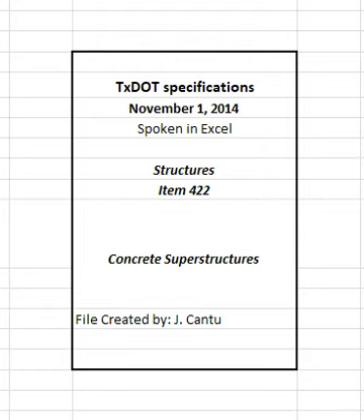of the mat. Provide polyethylene sheeting that is at least 4 mils thick and free from visible defects. Provide opaque white sheeting when the ambient temperature during curing exceeds 90 degrees Fahrenheit. Provide burlap polyethylene mats made from burlap impregnated on one side with a film of opaque white pigmented polyethylene, free from visible defects. Provide laminated mats that have at least one layer of an impervious material such as polyethylene, vinyl plastic, or other acceptable material, either as a solid sheet or impregnated into another fabric, and are free of visible defects.